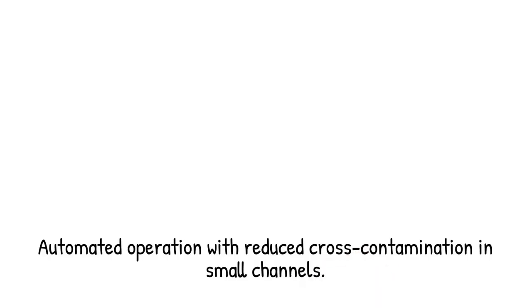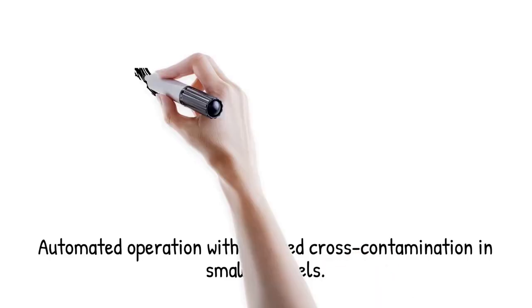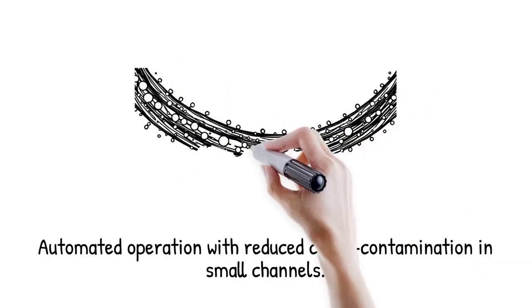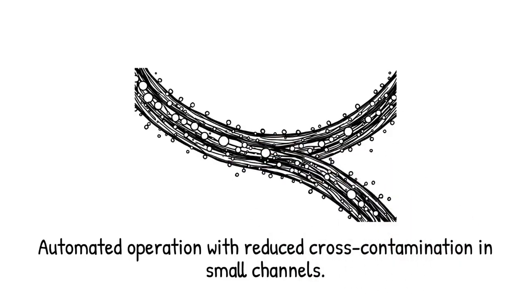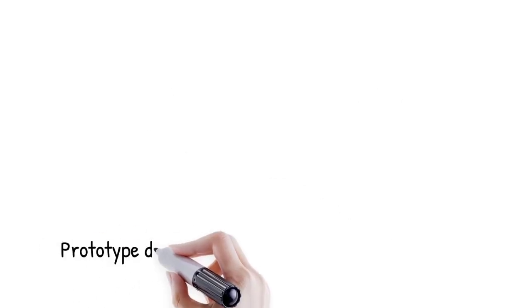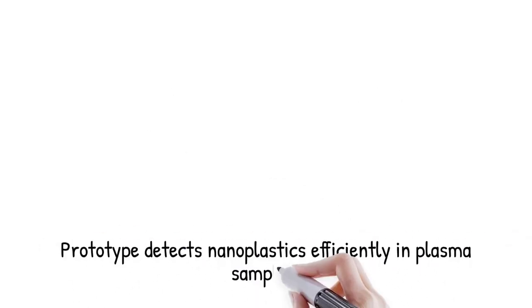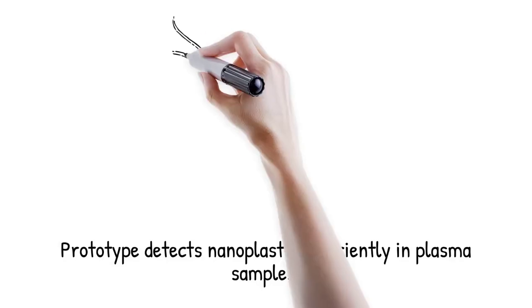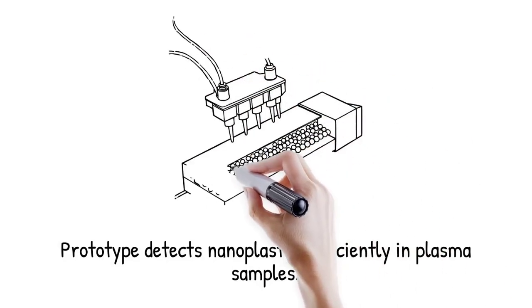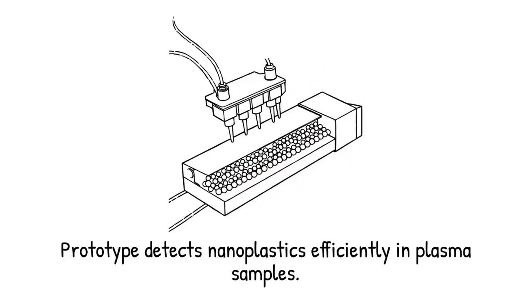Flow rates and laser positions are computer-controlled to balance trapping stability. This integration allows automated, hands-free operation compatible with clinical workflows. The small channel dimensions also reduce sample-to-sample cross-contamination. A prototype device processed 50 µL of plasma in under 10 minutes, detecting nanoplastics at concentrations as low as 10 particles/ml. It's like a high-speed assembly line sorting and inspecting tiny beads one by one under a microscope.